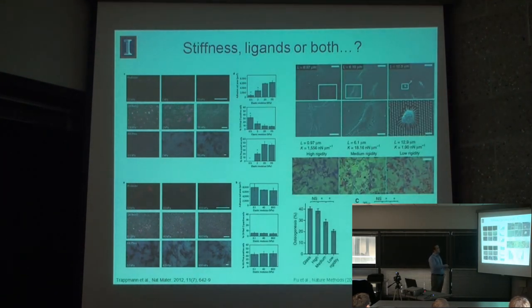And in terms of this question, I'm sitting more here, where I think that clearly these things play different roles. So this was a paper done a couple years ago with Fu and Chris Chen at Penn again, where they used these elastomeric micropost arrays that they have. And they did a really cool trick where they just changed the height of these posts. And so the mechanical properties of the material is the same, but they're just changing the height such that the stiffness that the cell sees is different across these.